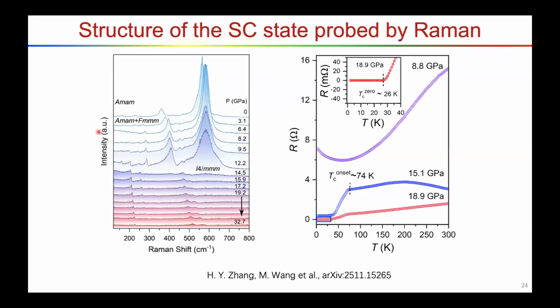And we measured our sample with Raman. With Raman scattering, at different pressures, we see a dramatic change in the spectrum above 14 gigapascals. That's the pressure where the superconductivity emerges.